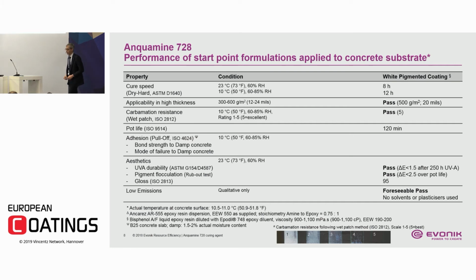You have a 2-hour pot life in this case, and you see some aesthetics data there. UV. This is obviously not a PU system, so for epoxy technically this is quite good, much better than solvent-free. But in terms of PU, this is obviously off the scale. So you have to put it in perspective. It's a pretty good UV in the epoxy range, and again high gloss, and the same thing for the low emissions that you can apply, these are very promising for low emission systems.